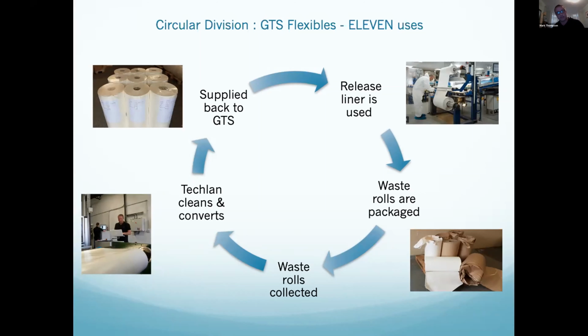We then send a truck in to collect the pallets and we bring them back to our site in Swansea. We then clean that product through our process. We convert it, we put good tensioning into the rolls, give bookend profile, and it's almost like a new product going back to GTS. Now, that product at the moment, once it goes back into that cycle, we're achieving 11 uses from the same release liner. They're manufacturing a laminated composite, whereas they were using 11 different release liners, they're now using one release liner 11 times.